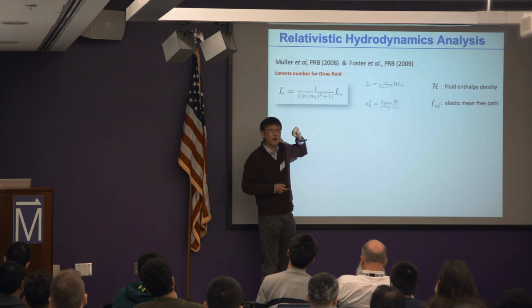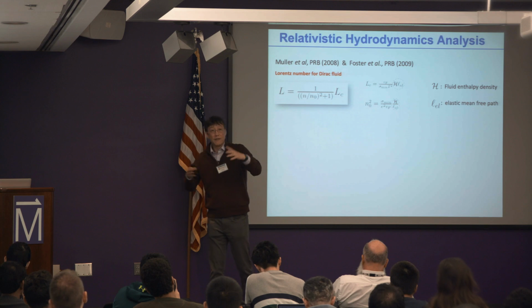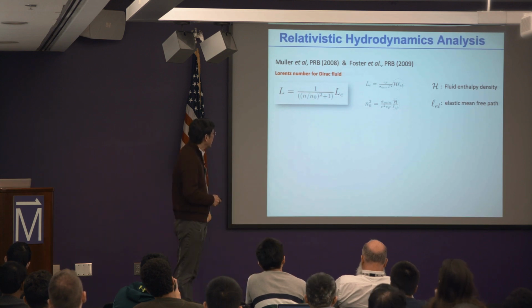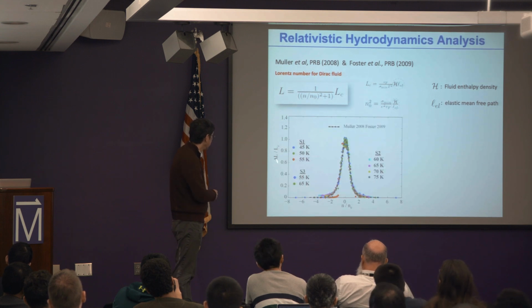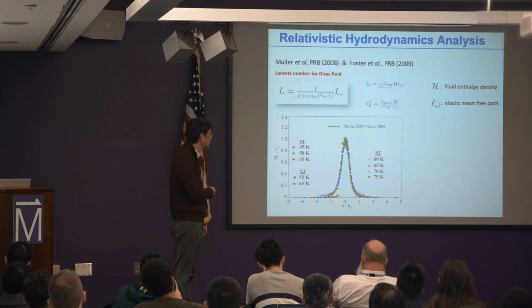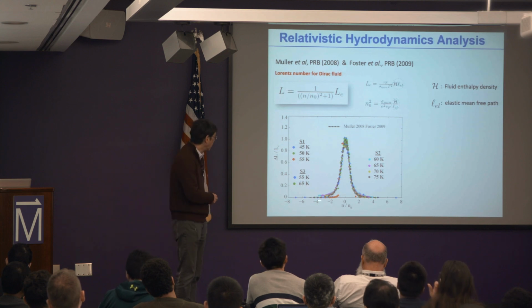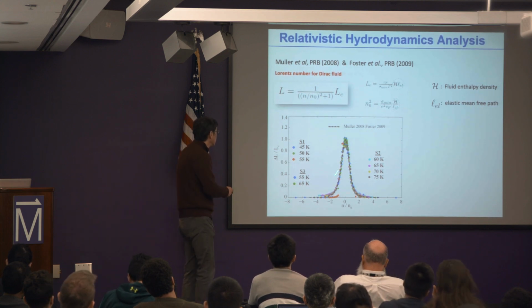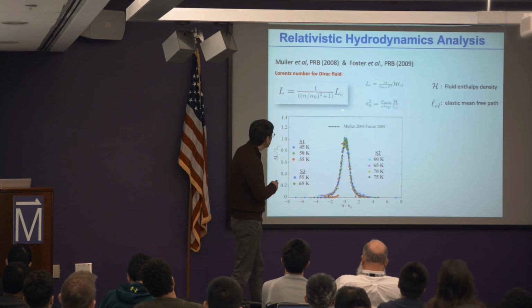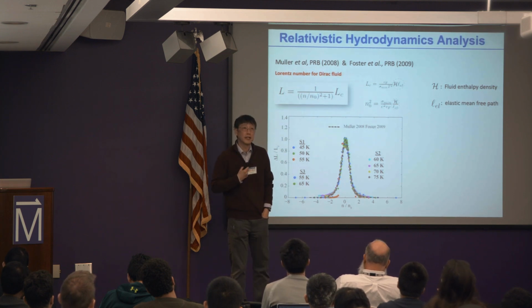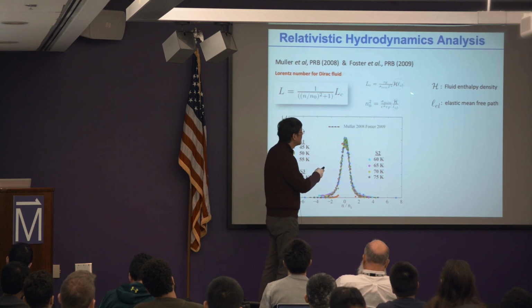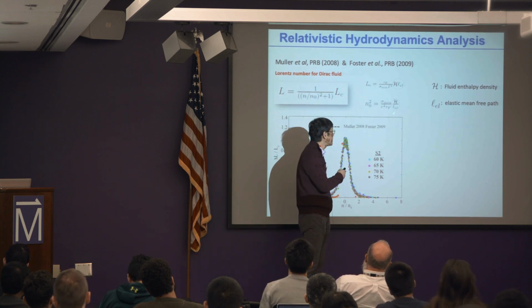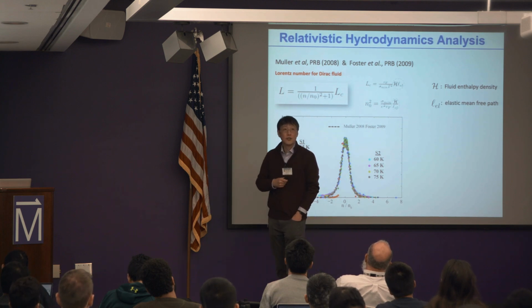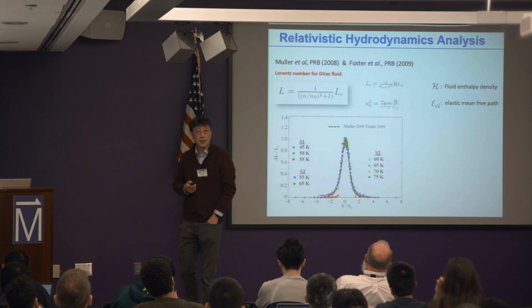And a nice scaling law is expected with the various ranges of disorder in the system. So following these theoretical descriptions, we plotted out L over L naught, L over LCs, and we can collapse all the samples with different types of disorder. And amazingly, many samples actually fall onto this universal curve we plotted. This universal curve contains two fitting parameters. One is the enthalpy of this Dirac fluid, and the other is the scattering length of the electron to the impurity that changes the conductivities.